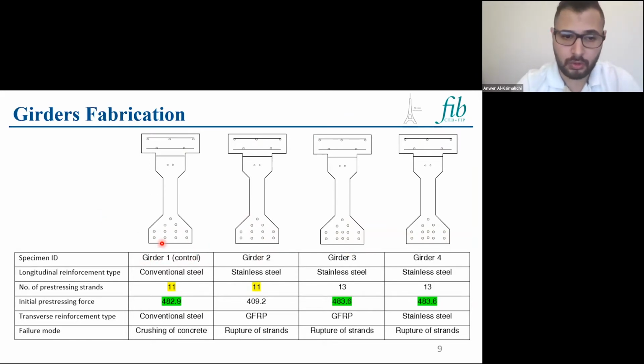The first girder is the control girder. It had 11 conventional strands, and conventional steel rebars for transverse reinforcement, the stirrups. Girder 2 had stainless steel strands. We matched the number of strands with the control girder. Girder 3 had the same initial prestressing force as the control girder, so we had to increase the number of strands to 13. Girder 3 and girder 4 are identical, except that girder 4 had stainless steel rebars.